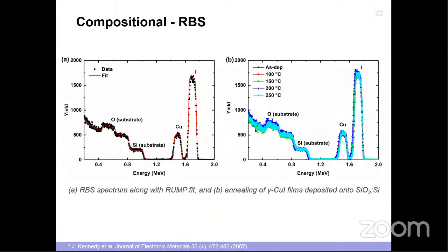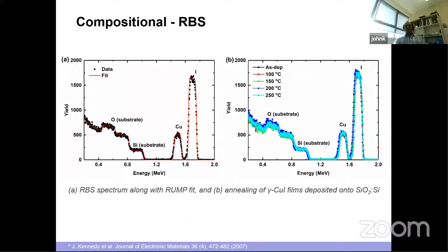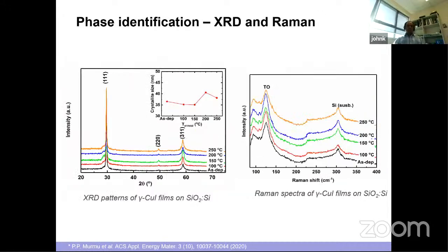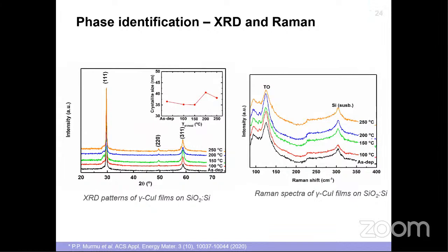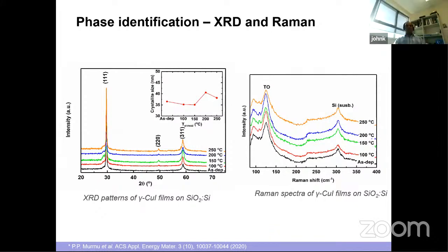As usual, you look at the stoichiometry of the film. We use the famous Rutherford backscattering spectrometry technique, and the stoichiometry is maintained even when the samples are annealed in argon at 100 to 250 degrees C. The stoichiometry did not change much. There's a slight change after annealing. What is interesting is that if you look at the XRD, which is a GA-XRD, the 111 reflection dominates the nanostructured gamma copper iodide. It originates from the stability energy associated with the growth of crystallites along the 111 direction. So the film growth direction is basically caused by the formation of iodine vacancy defect states. You can also see the Raman feature around 125 that was assigned to the TO mode. It's also normally associated with gamma copper iodide.